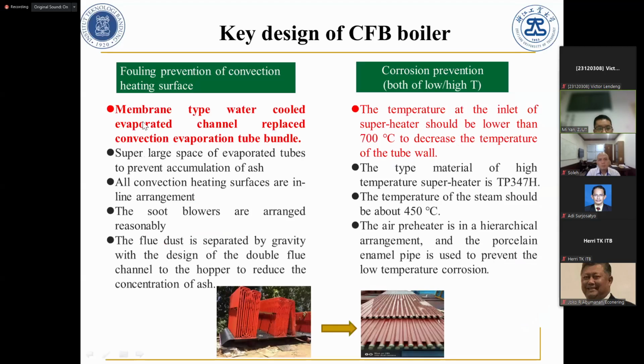And how to prevent fouling of the convection heat surface? So a membrane-type evaporator channel replaced the convection evaporator tube. At the beginning we used this kind, the convection tube. Now we must use this membrane type, called an evaporator. So it will reduce the fouling and the ash sticking to the surface. And the space of the evaporator tube is super large.